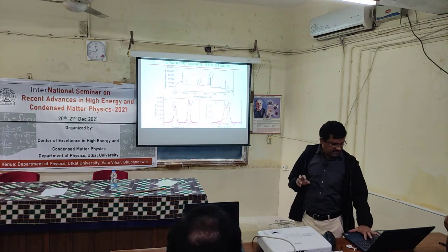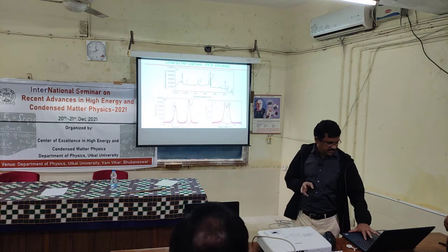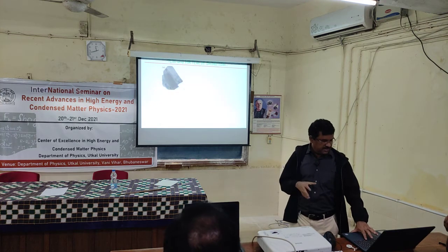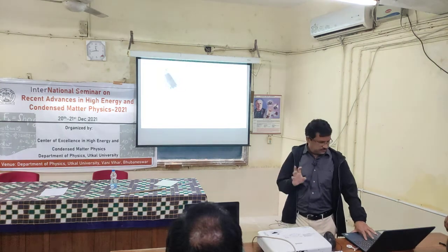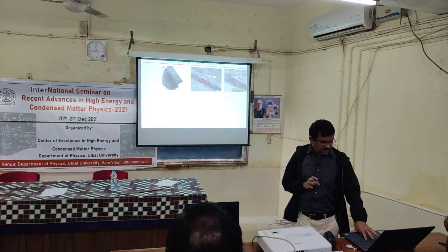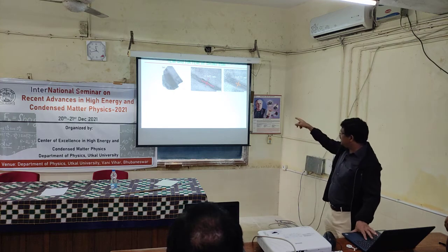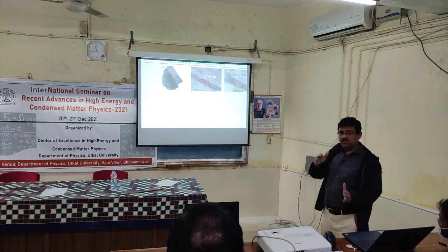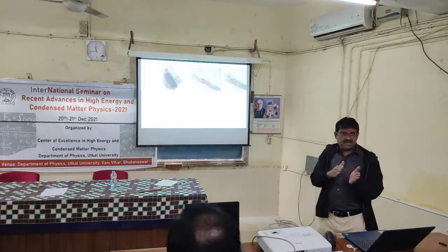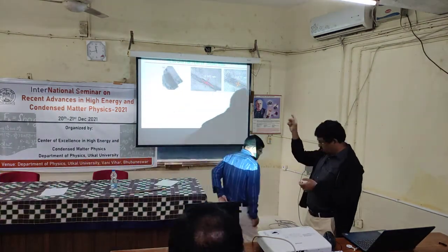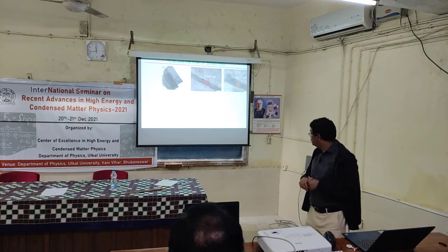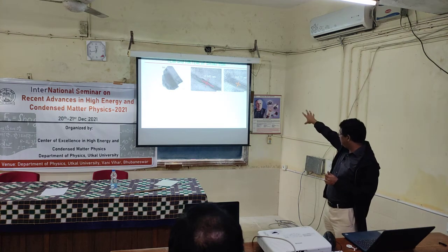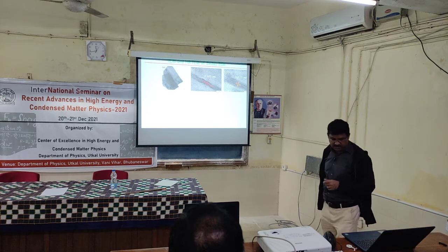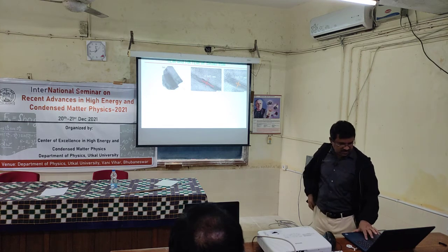So this is some characterization. This is XRD, this is XPS. This tells us that we have the formation of SnSe2. And there are some clear images, and you see here there are some layered structures. Okay, SnSe2 is a layered system like graphene, and the distance between two layers is around 0.64 nanometer. So in some places you can see it is 0.62, and in some places it is 0.64 nanometer.